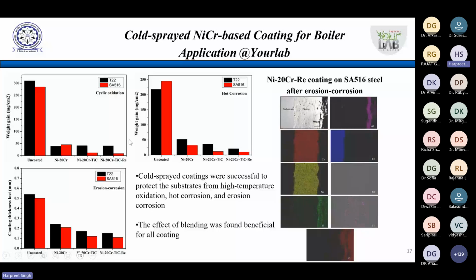In fact, we checked the weight gain, which is one of the measures just to check whether oxidation has taken place or not. Another thing is coating thickness measurement, right? We have made coating thickness loss measurements. When we hang the samples in the corrosive and erosive environment, especially this erosive environment is basically flowing parallel to the flat surfaces of the rectangular samples, and in doing that it will erode our samples and hence cause some thickness loss, right?